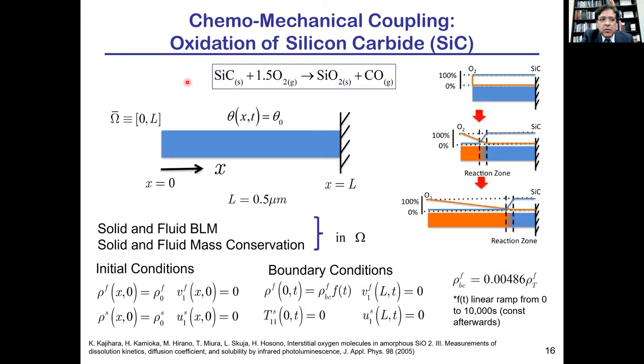The next numerical simulation is chemomechanical coupling in a mean background temperature that is sufficiently high so that it helps silicon carbide react with oxygen to give rise to silicon dioxide. And so this is the specimen. The material is open to outside oxygen. Oxygen diffuses through the solid. There's a chemical reaction taking place. This advancing front moves in, with reacted material and unreacted material.